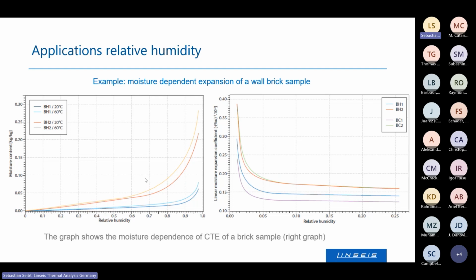So the blue one and the red one were two different samples. They both saw 20 degrees and 60 degrees, and at each temperature, the humidity was increased. After the experiment, the moisture of the material itself was determined by thermogravimetry.